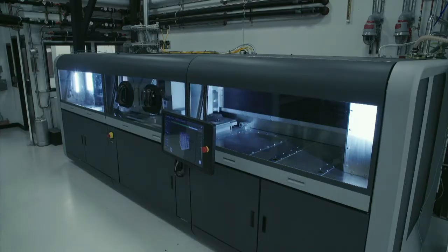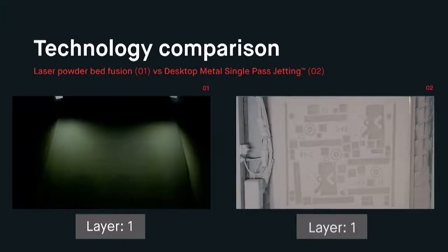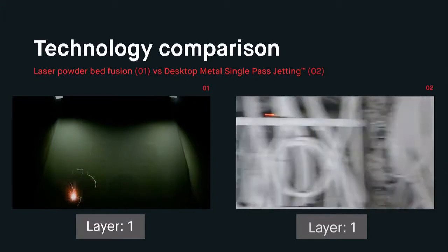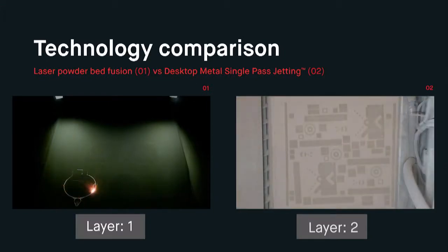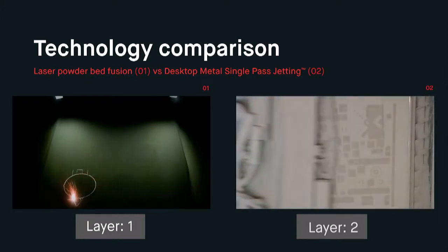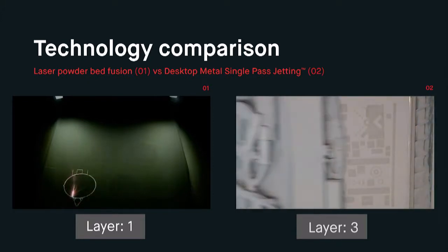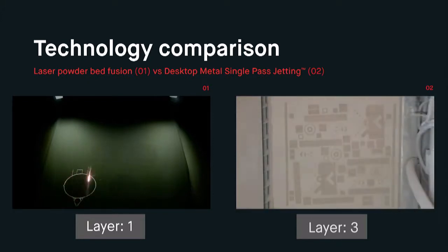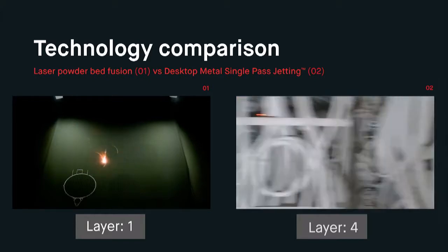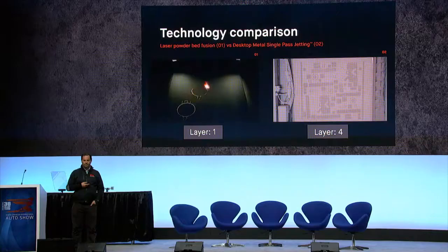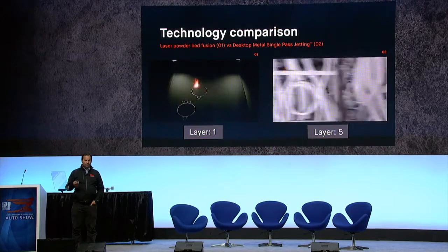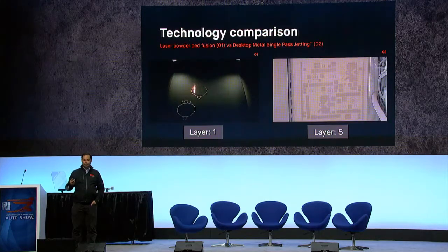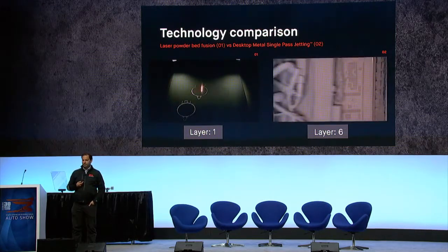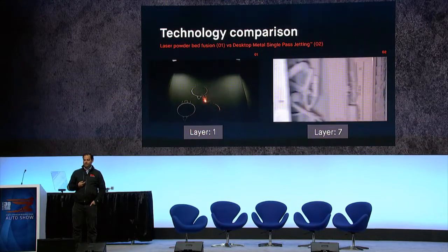You see some of the pictures here of the process. It is approximately 2 seconds per layer, which is very fast for an additive system. If you see here on the left, powder bed fusion is a vector-based process. It's kind of like comparing a dot matrix with a laser printer in terms of the throughput and the speed. And you're doing this with raw materials that are 80% cheaper than the raw materials that you'd be using in a powder bed fusion system.